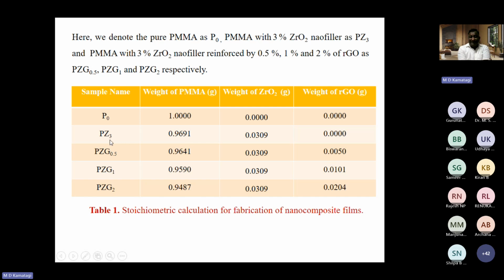This is 3%, the PMMA and ZrO2 nanocomposite, wherein there is no graphene oxide. This is a sample where the weight percent of ZrO2 is 3%, whereas that of graphene oxide is 0.5%. And this is graphene oxide 1%, this is graphene oxide 2%. So we have varied the graphene oxide weight percentage from 0.5% to 2%.